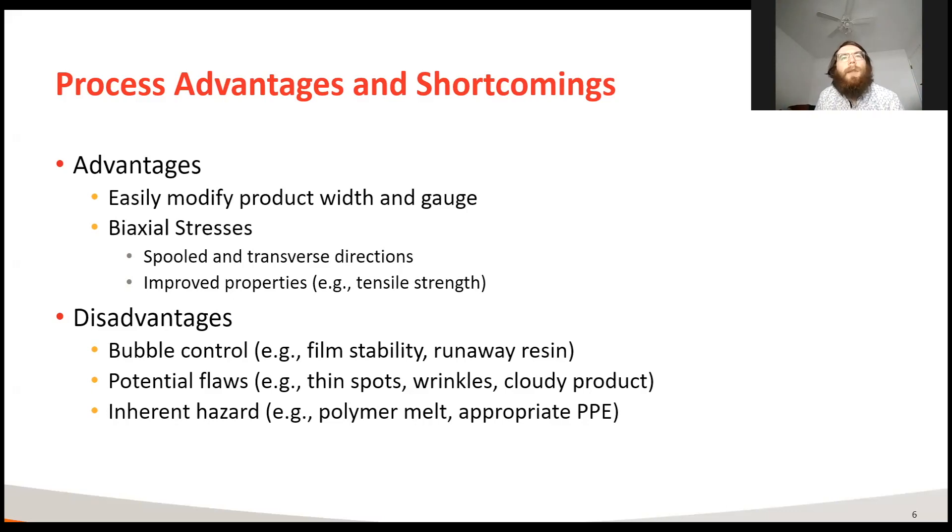Additionally, the process is prone to flaws such as wrinkles, which may occur during the bubble collapsing process. As well, the process generally produces a cloudier product due to lower cooling rate when compared to processes which employ chill rollers or quenching.